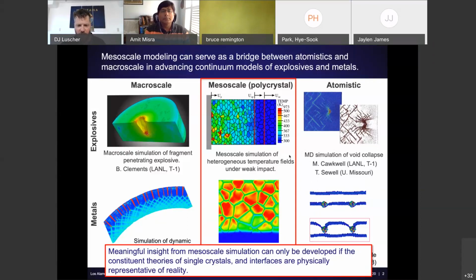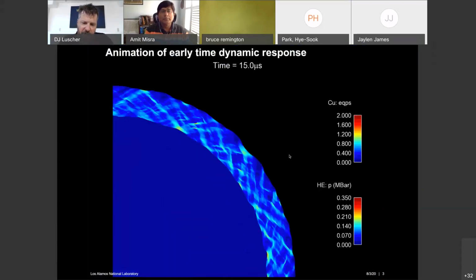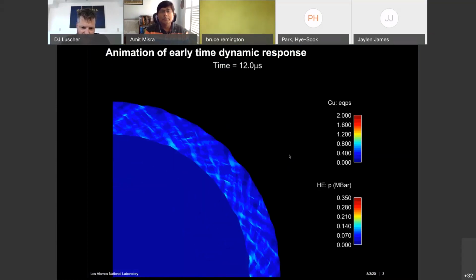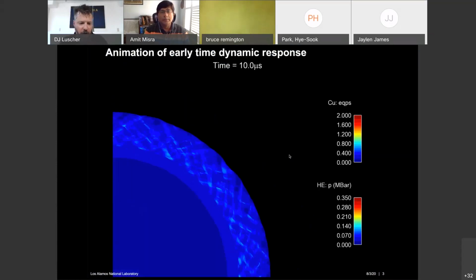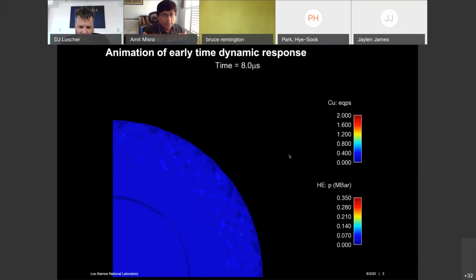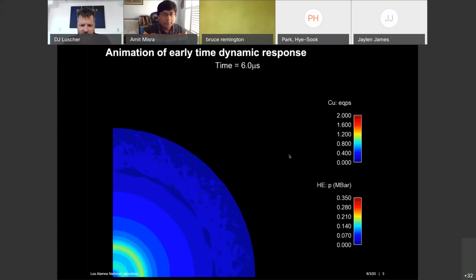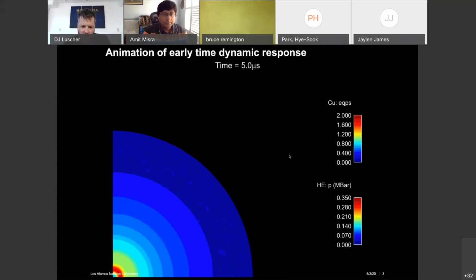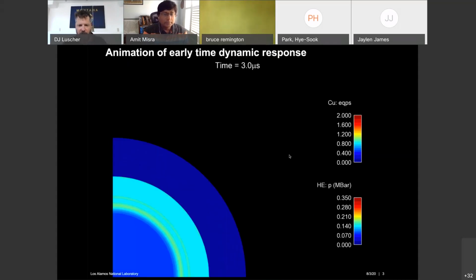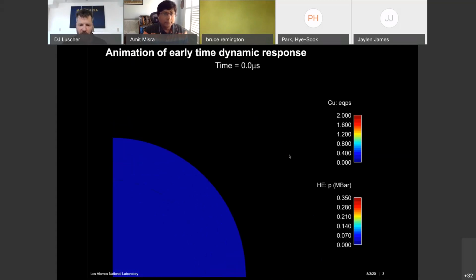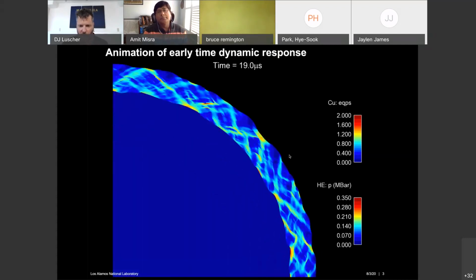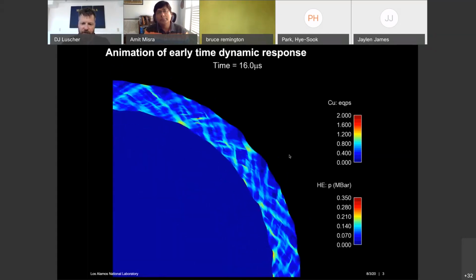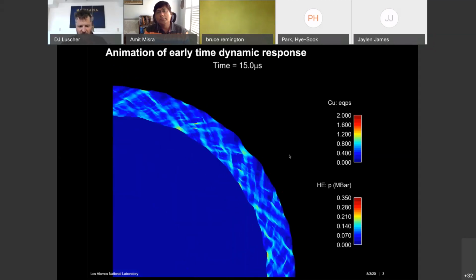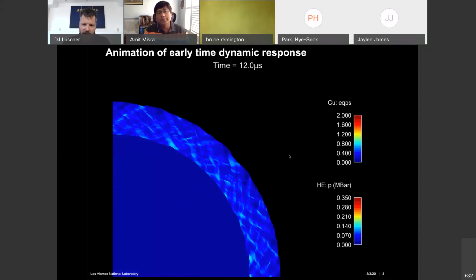And now the next slide, I'm just going to reinforce our interest in applying these kinds of tools to shock physics applications. In this case, we have an explosive at the center of the screen that's being detonated. Well, not the center, I'm sorry, the lower left corner, but it's the center of this quarter symmetry cylinder. The explosive gets detonated, and that sends a shock wave, which pushes a thick copper-walled cylinder, and it's then plastically deforming. And because of the role of the microstructure, we see heterogeneity in this calculation that emerges, and that leads to the formation of localized flow and necking, which ultimately is significant in terms of defining the fragmentation pattern.